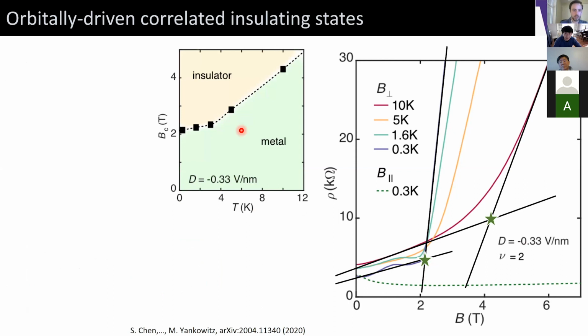And we can make a phase diagram here, and what we see is basically that the critical field grows weakly with temperature as we start to warm the system from base temperature, and then starts to grow quickly at high temperature. And below this line, we have a metallic state, and above this line, we have an insulating state, as defined by how they respond to temperature.